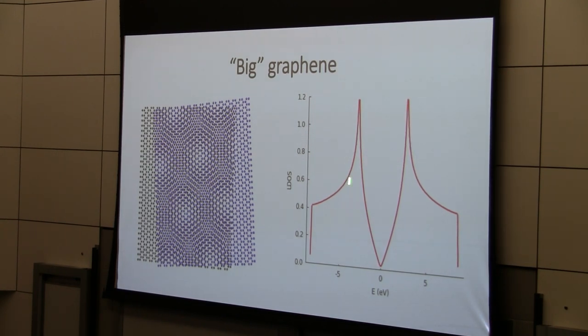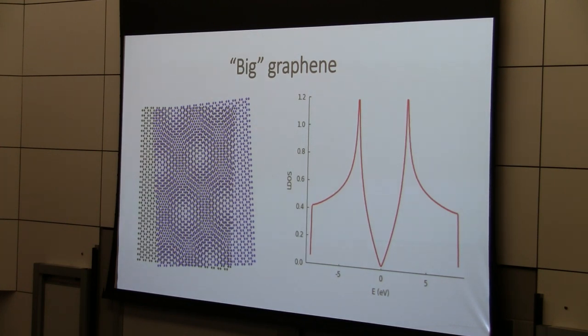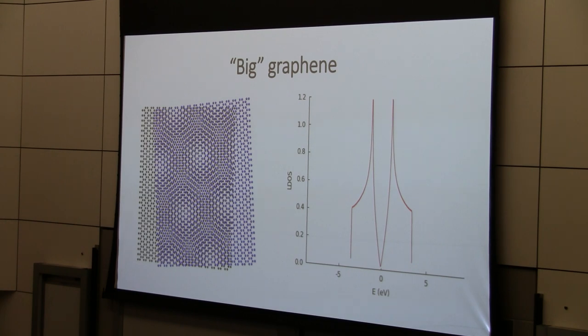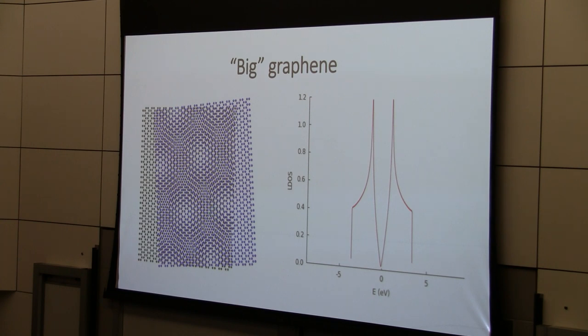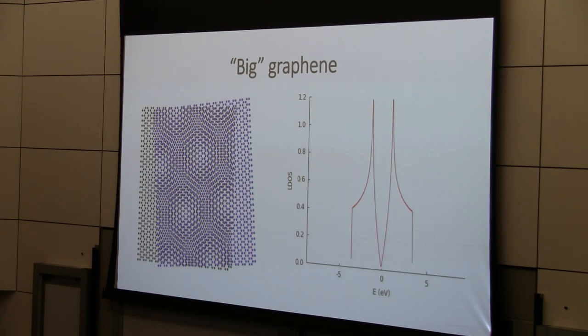And so what this does, if I look at the density of states, since this distance from here to here is proportional to that lattice constant roughly, if I make the lattice much bigger, I make those two things come closer. And so if you follow this logic, then as you make this twist angle smaller and smaller, this wavelength of the Moiré pattern becomes bigger and bigger, and these two singularities in the density of states start to come closer and closer together, and as you get to extremely small angle, they should more or less come very close to the Fermi level.